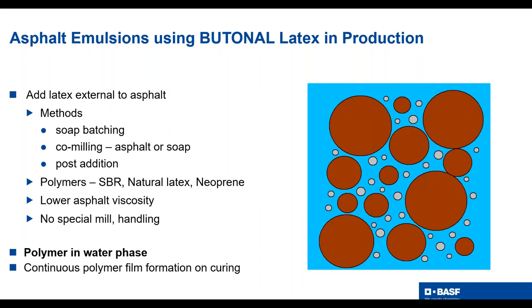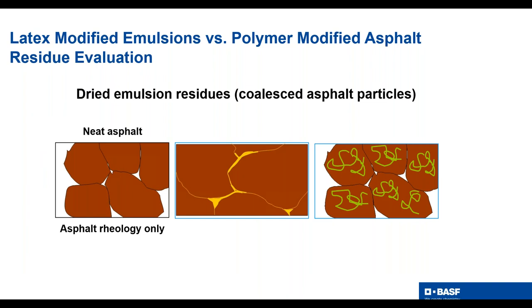But the benefits of running the solution is you can run the latex as part of the solution. You have a lower viscosity. You're basically not having to heat the asphalt as hot. You don't have a special mill to make the emulsion. Handling the emulsion is fairly easy. So the polymer, again, is in the water phase, and so you can get a continuous film around coating and curing. Here's a picture that gives an example of that, how the asphalt coalesces.